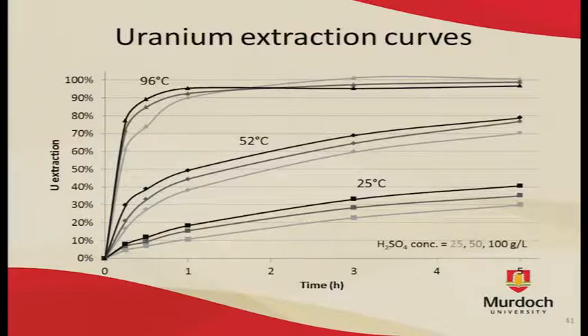The main focus of the study was, of course, the kinetics. So these were some of the uranium extraction curves. The high temperature curves are at the top, the 52 degree leach curves in the middle, and the 25 degree leach curves at the bottom. I've left off the 36, 63, and 79 degree ones to avoid cluttering the slide, but they all fit the same sort of trend, with darker lines corresponding to higher acid concentrations. Just from this, it should be apparent that increasing the temperature had quite a large effect on the rate at which uranium dissolved.